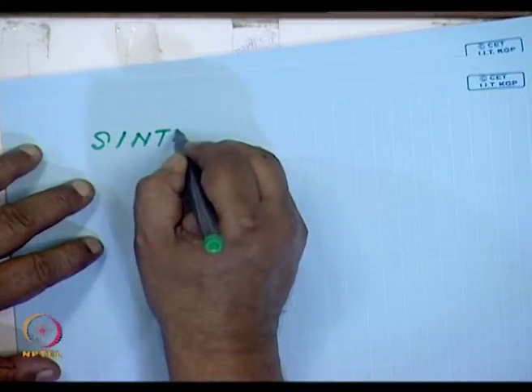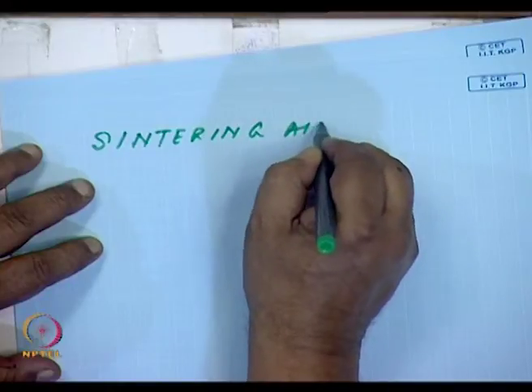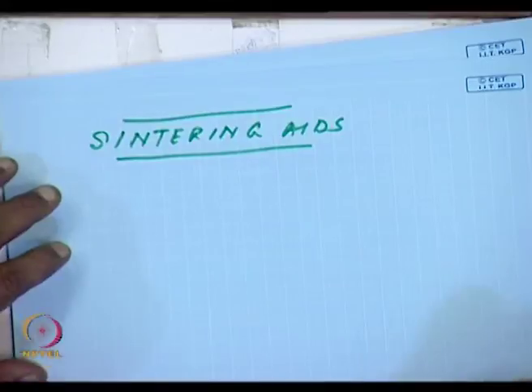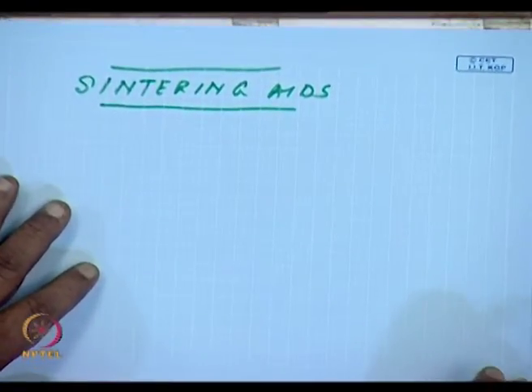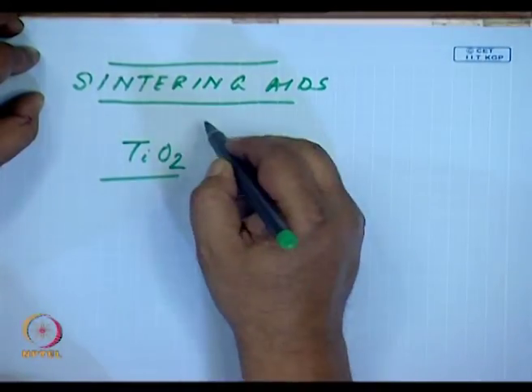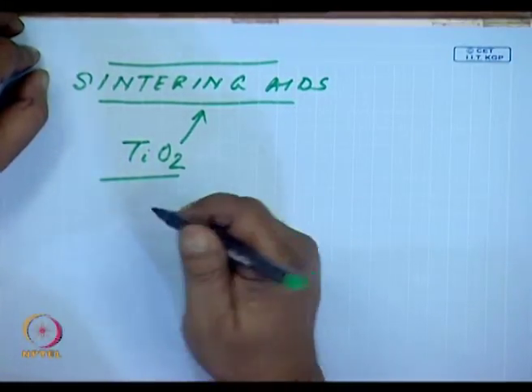During sintering, one of the things we use are materials like sintering aids. These help in sintering, because sintering is nothing but a diffusion process, and we have to find ways to enhance the diffusion rate. For example, the sodium vapor lamp, which uses alumina, uses TiO2, titanium dioxide, as a sintering aid, because otherwise much higher temperatures would be needed to densify the alumina.